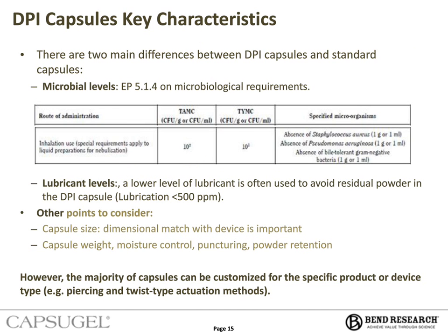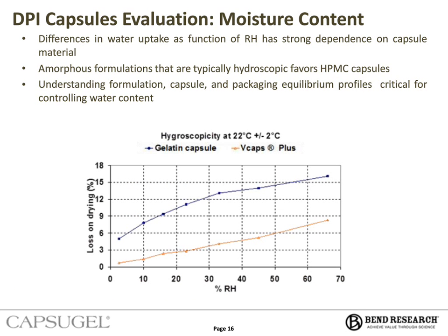So just to illustrate a little bit the importance of the choice of capsule in relation with the moisture content, it's clear that a lot of formulation for inhalation may be hygroscopic, may be sensitive to the moisture content, and it is important to know the difference between the gelatin capsule and the HPMC capsule. On the slide here, you have a graph which gives you the moisture equilibrium between the relative humidity of the air and the moisture content of the capsule, expressed as Loss on Drying oven method.